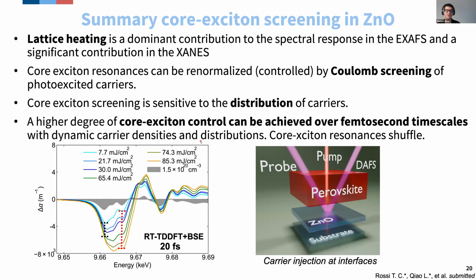And the final thing is that my colleague was able to simulate what would be the result of an XFEL experiment. So this time, instead of using the constrained DFT, she used a real-time TD-DFT and then ran the Bethe-Salpeter equation on it. And that's typically what you would get on a time scale of 20 femtoseconds at increasing fluences. And now what you can see is that the line shape becomes quite dependent on the density of carriers that you put in your system as you increase the fluence. So for instance, there is a large change of relative amplitude between the features. And what this indicates is that individual excitonic resonances start to shift by different amounts. And by doing so, this is one way to actually individually control them. So I think there are great promises by doing experiments on femtosecond timescale if we want to achieve an even higher control over these core exciton resonances.